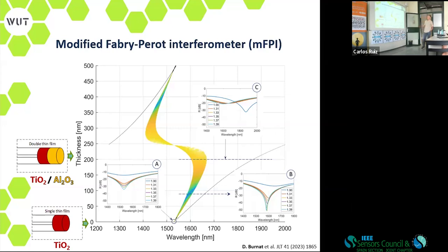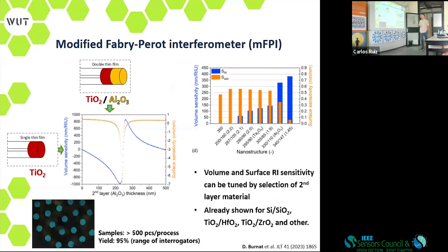When we deposit more and more of this secondary film, we see that we get more sensitive structures to the index, but it's shallower. By analyzing this structure, we analyze the sensitivity volume, the one that gives the refractive index response, and the sensitivity to the position of the film on the surface. So the thickness of each material extremely changes the properties of this device. Unfortunately, it's not that deep, so mostly we need to work in this range where the sensitivity is somehow boosted by this film. And we analyzed different materials as the secondary film, and it seems that we can slightly improve the sensitivity to formation of the biofilm on the surface by application of certain materials.